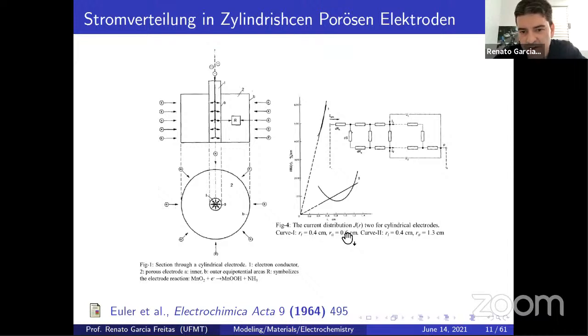However, if we increase 0.6 centimeter up to 1.3, we have a change of the profile, like obtained here. So for small pores, the transmission line works pretty well, like we see here in function 1. And in 2, when the outer radius increases from 0.6 up to 1.3, it looks like function power 2, but indeed we have this profile because the hyperbolic cotangent decreases, so we have positive and negative values. So it already gives insight into the morphology of power change and changes the equivalent circuit, the transmission line, and only for very small pores, as soon as we decrease the radius of this pore, we have a better fitting of this parameter.